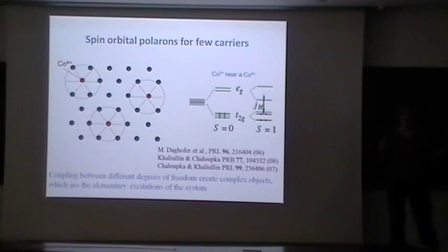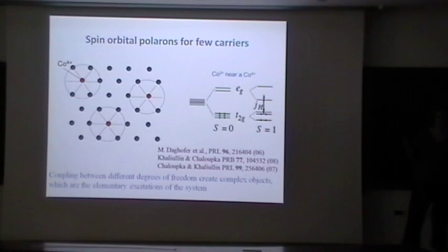Yeah, but it depends. When you try to do this fitting, it's always a little bit difficult, because the moment you get depends very much on the Curie-Weiss temperature you get. So it's consistent, but it's not completely straightforward to interpret. It depends a little bit on what you choose as Curie-Weiss temperature.